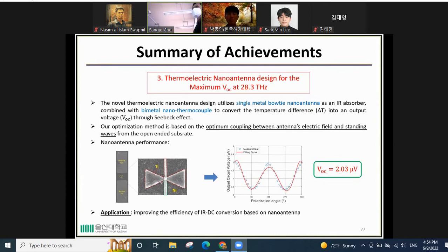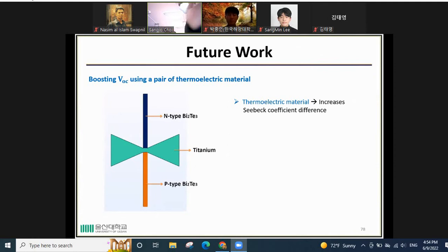This is the fabricated nano antenna. Our antenna is showing 2.03 microvolts in the measurement. So in the application, this structure can be used to improve the efficiency of IR-DC conversion based on the nano antenna. In the future work, I'm considering how to push the VOC of the thermoelectric nano antenna. Instead of using metal for the nano thermocouple, we can use thermoelectric materials such as bismuth telluride for P-type and N-type, because these two materials have a higher Seebeck coefficient to increase the output voltage.